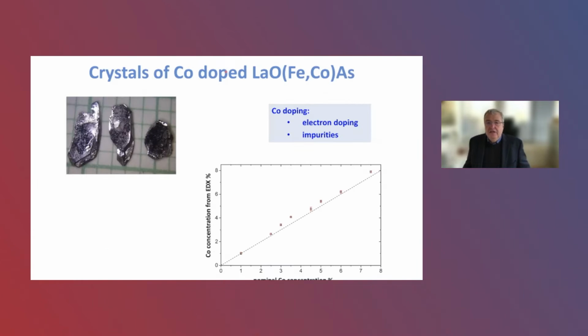Still, the challenge is that doping with fluorine is extremely difficult, and we are still working on that. There are some first progresses, so replacing oxygen by fluorine in this process, but the control for that we still do not have. What is easier to do is to replace iron by cobalt. So then we can use the same process. We can produce single crystals now. The cobalt concentration which we found in the crystals corresponds very well to the nominal cobalt concentration which we use to synthesize the crystals. So that's shown on this line.